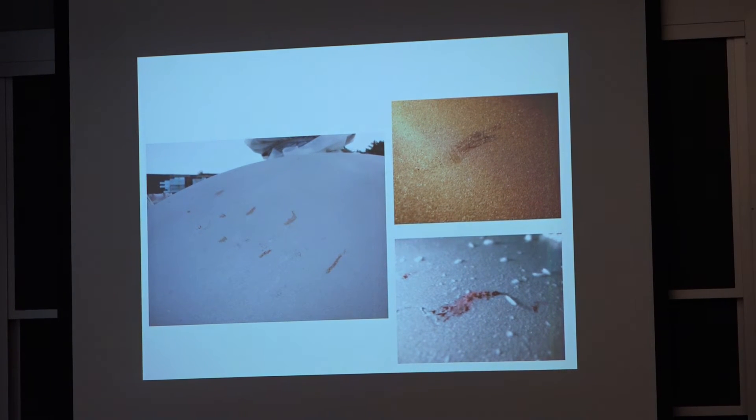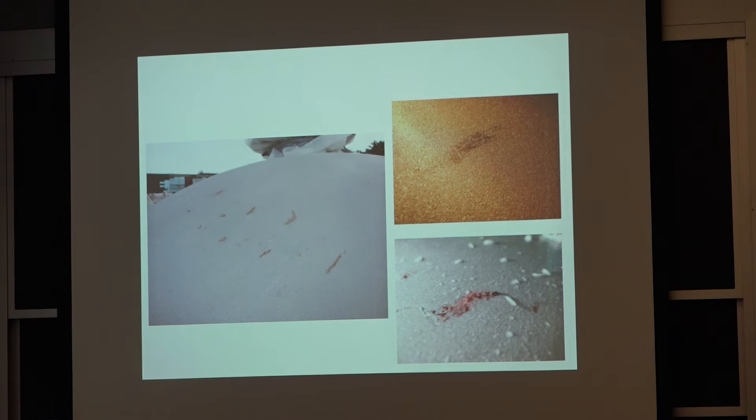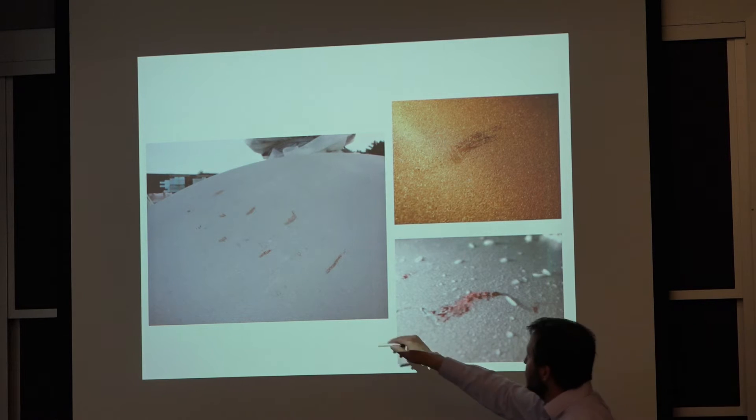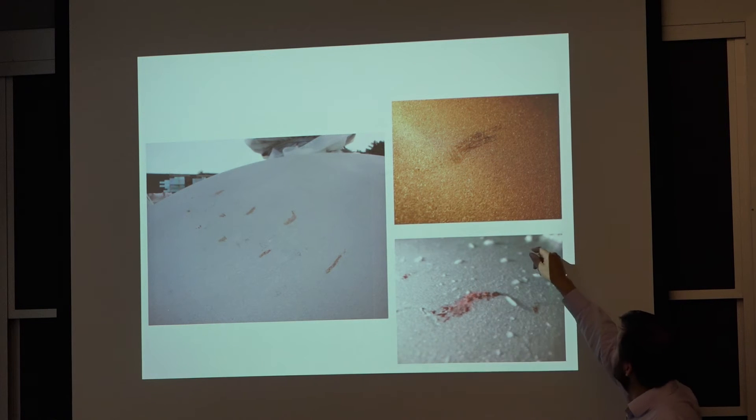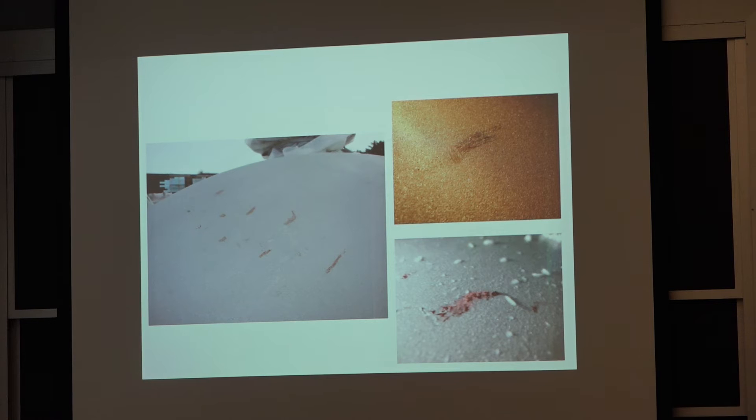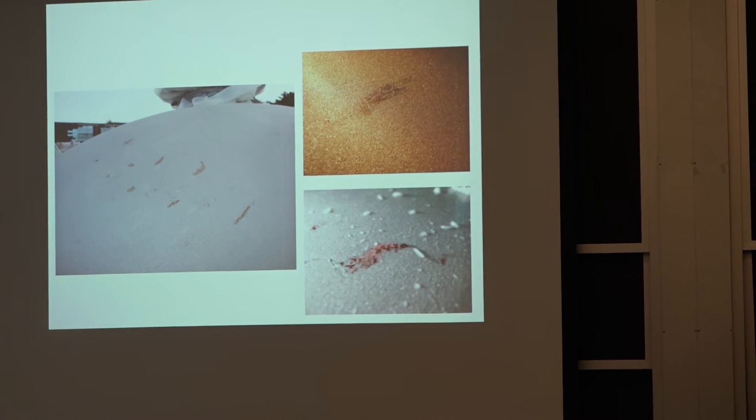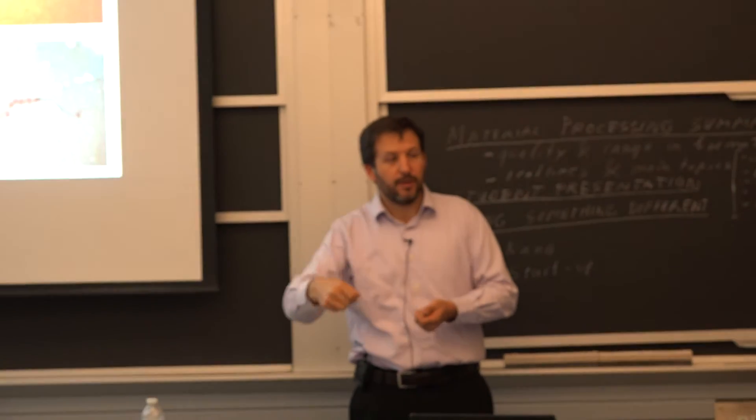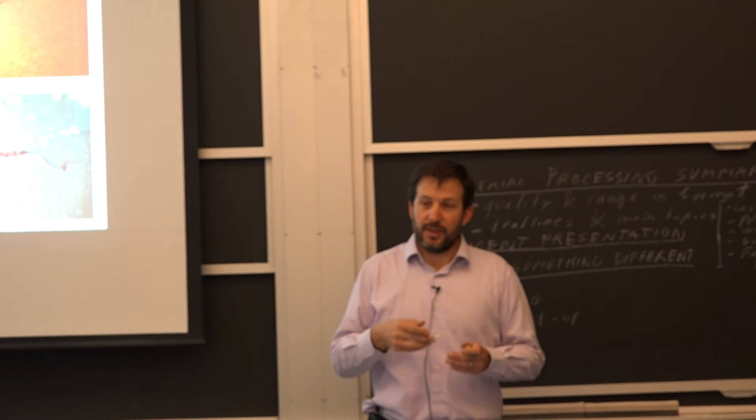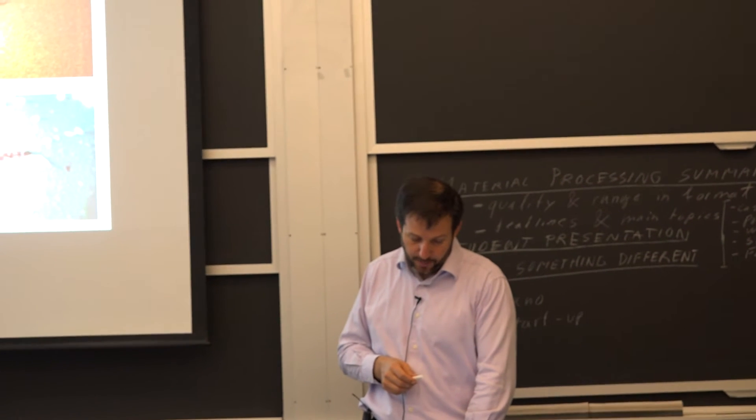For appearance we've talked about stainless steel. One common problem with stainless steel is contamination with another steel. So let's say you're trying to assemble something out of stainless steel and you use a hammer or wrench that's made out of regular steel. You can contaminate that surface. This is a big pressure vessel on the surface. You see the rust and there's a test where you clean that surface and then you put a little bit of an etchant solution. When it turns pink like here, you know it's because you have iron contamination.